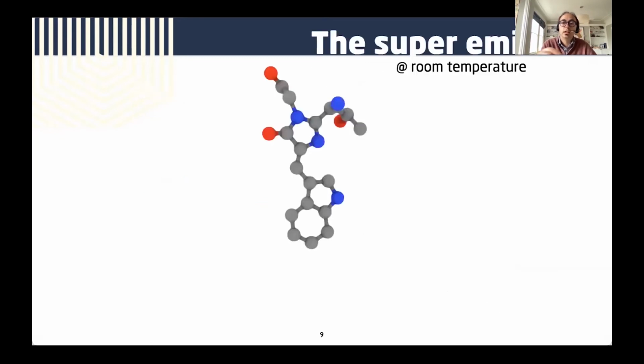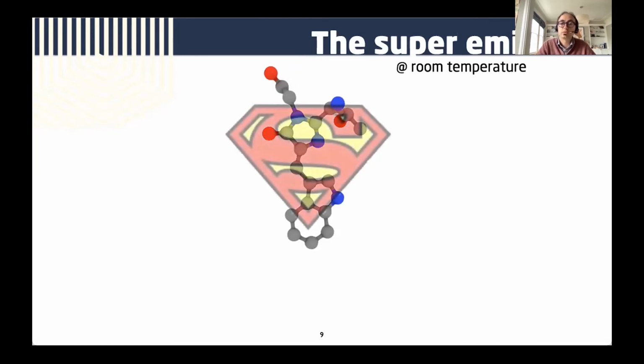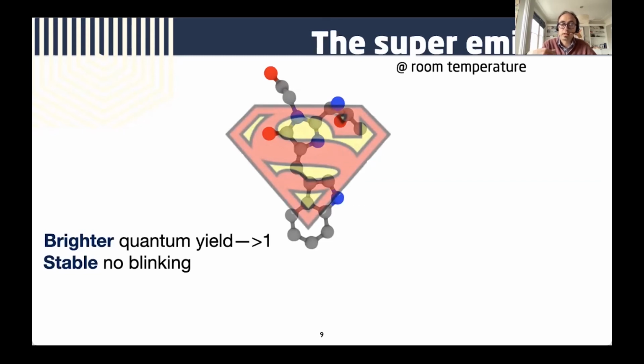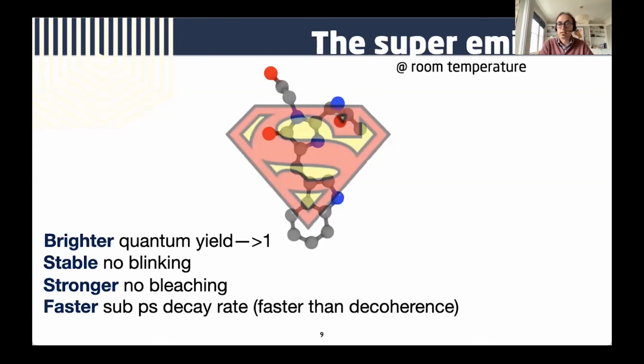And the goal here is that we take an emitter which has its own properties. Now here it's drawn as a molecule, but it can be any emitter. And then by placing it in the right photonic environment, we can make it into a sort of super emitter, an emitter that has much higher quantum yield, which can approach 100%, that could be stable, typically enhancing the photonic transition. We are decreasing the probability of going into dark states or blinking or other processes. And therefore the bleaching also is reduced. So the photonic process will be more and more optimized. And also we can make the emission faster and faster, which means more photons per second. And in some cases, it means also an emission faster than the coherence time. That's at least in theory.